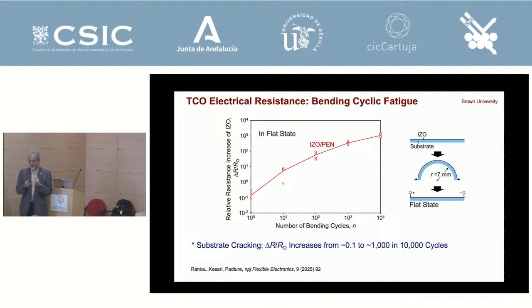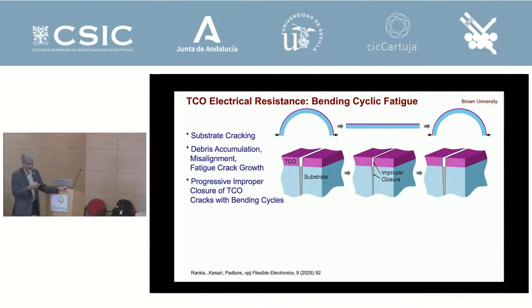The hypothesis for why this is happening is that when you bend it, the film cracks, the substrate cracks, then when you make it flat, the film comes together, there is contact, there's no infinite resistance, there is some conductivity, right? But because of the substrate cracking, every time you do this, it's not closing quite properly because you can get debris and the closing is improper. And this has been shown in other systems, in metals and things like that. And so therefore, the resistance keeps increasing with the number of cycles because you cannot close and make the contact.